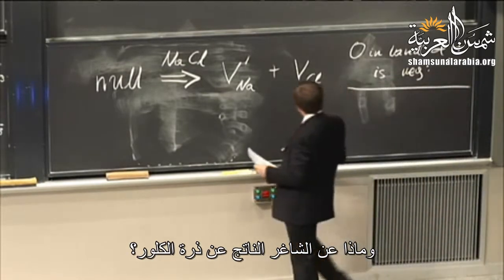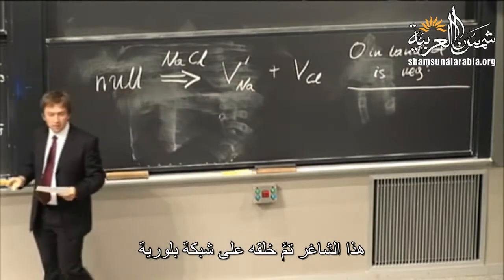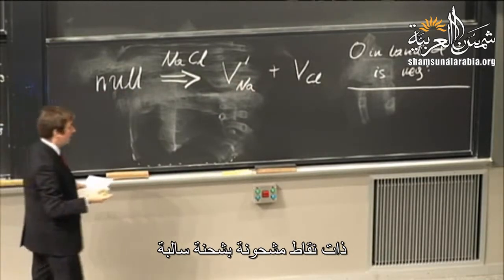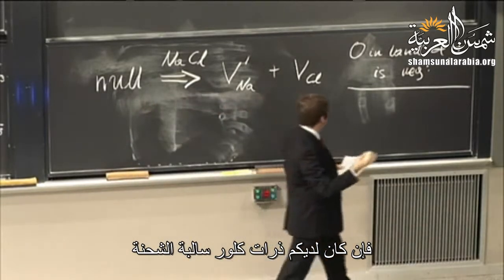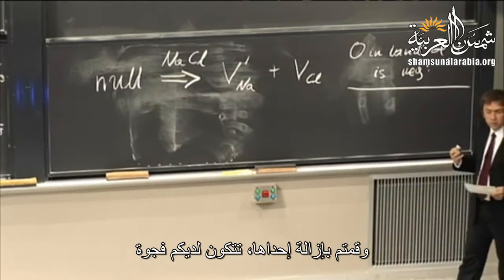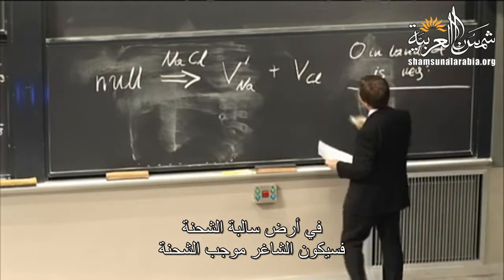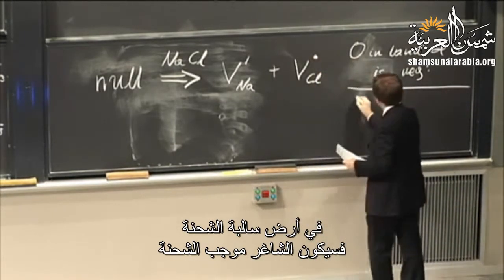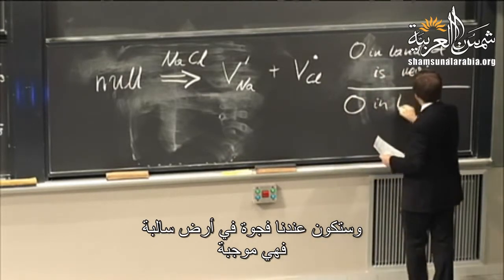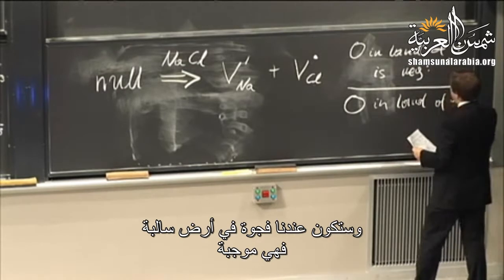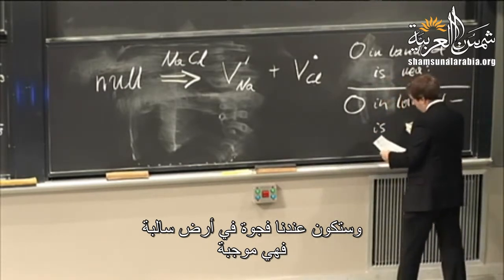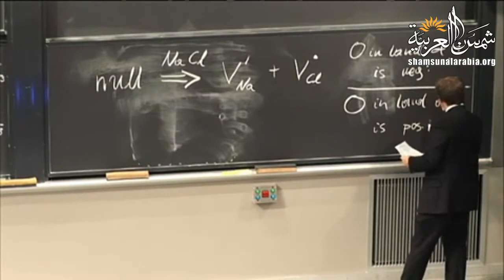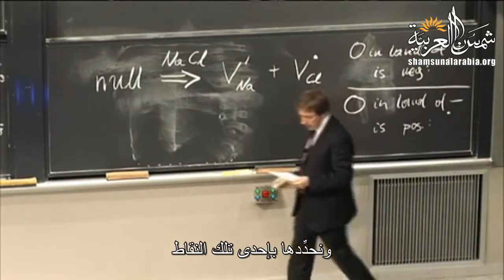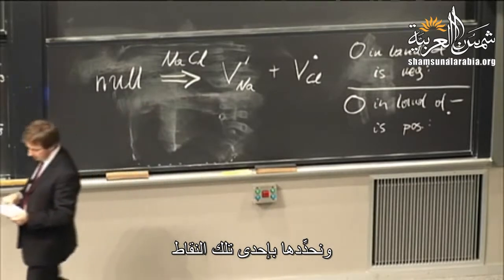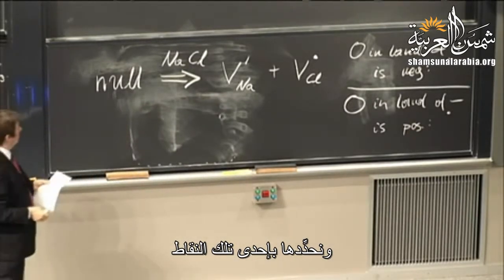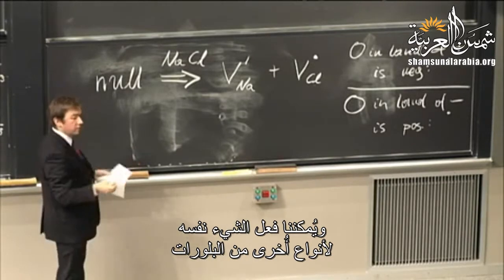So what about this vacancy? That vacancy is created on a lattice of sites which are usually charged negative, right? So if you have these chlorine atoms that are charged negative and you remove one of them, now you have void in a land of minus. So this is going to be effectively charged positive. And so we have this void in land of minus is positive, and we annotate it with one of these dots. We can do the same thing for other kinds of crystals, right?